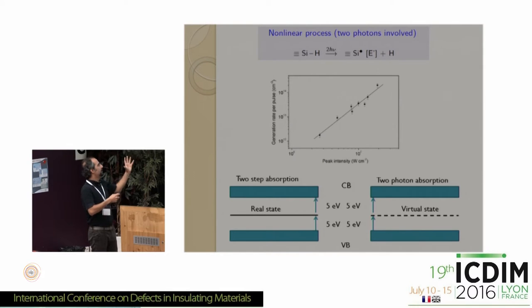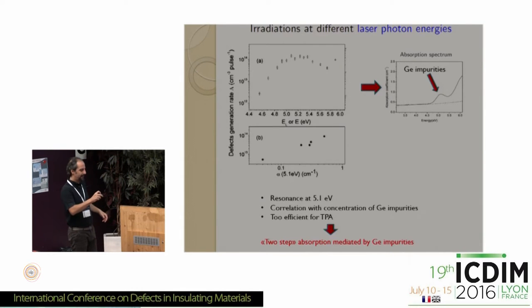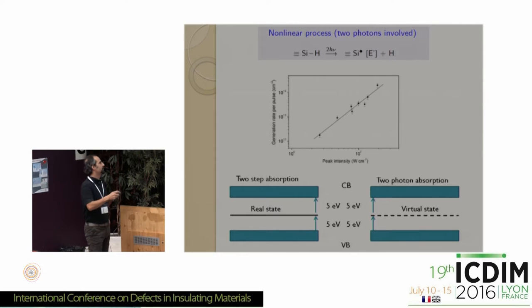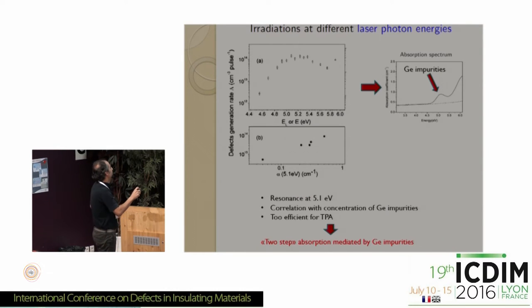Now, we wanted to understand which of the two is involved in our case. First of all, if you do some math, you can easily demonstrate that at the laser intensity we were using, two-photon absorption is quite unlikely. So this brings you to suspect that two-step absorption must be involved. Another way of investigating this is to study the process as a function of laser wavelength. Because if there is a real state in between, it probably means you need to see a resonance where you hit the real state, okay? So we did this experiment.